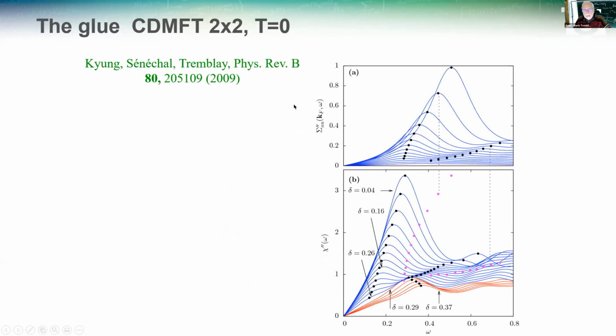So back to our problem in the one-band model. Again, I plot the imaginary part of the Cooper pair self-energy as a function of frequency. And again, there are two peaks. Now this time, not the phonon density of states, but I plot the imaginary part of the local spin fluctuations. In other words, the spectral weight for spin fluctuation, double prime. You see that there are two peaks there.